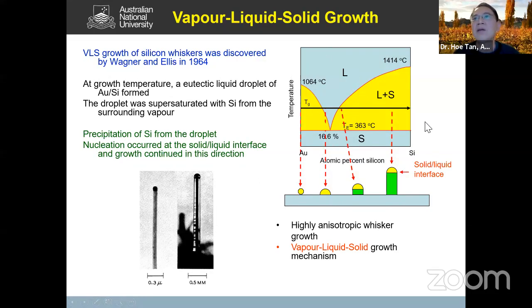If you look at this plot here, this is the temperature versus gold and silicon composition. So this is essentially the phase diagram. If you're working at an elevated temperature and you're passing the silane vapor, the silicon vapor, so this is 100% gold, 100% silicon, the gold is gradually absorbing the silicon atoms. So it moves along this line until it hits this point here where it forms a eutectic, a gold-silicon eutectic, a liquid. Because it becomes a liquid, it wets the surface of the silicon wafer.